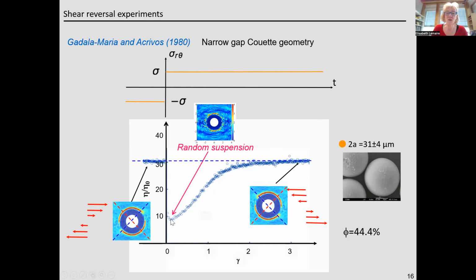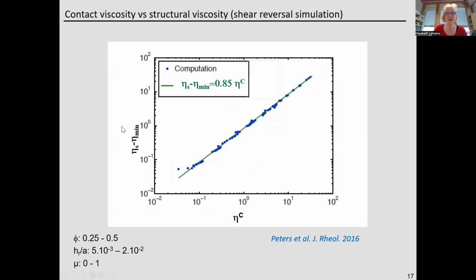the minimum viscosity is almost the contact contribution to the viscosity. And this has been checked by numerical simulation. And in fact, we observe that the difference between the steady viscosity and the minimum viscosity is 85% of the contact contribution to the viscosity. Okay, so these shear reversal experiments are very good ways to evaluate this contact contribution to the viscosity.